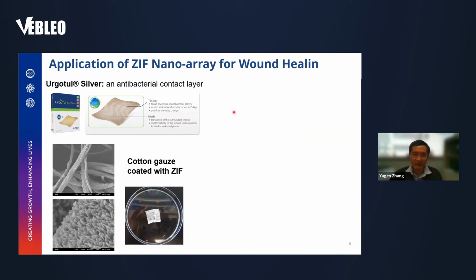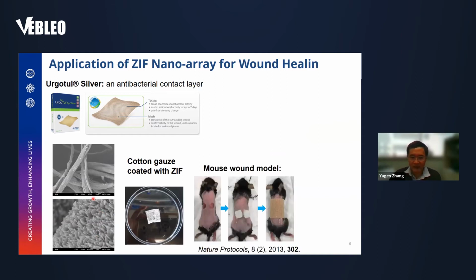Showing here is one application example. So we know that for wound healing, there's a commercial product. They use silver as the antimicrobial contact layer. But here we take a cotton gauze. We just coat this ZIF nanostructure on the cotton fiber, and showing here the SEM. And then we use this for covering the wound, develop this wound model, and then compare with the commercial one.